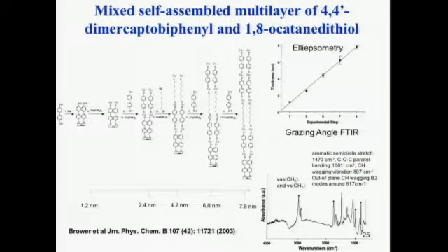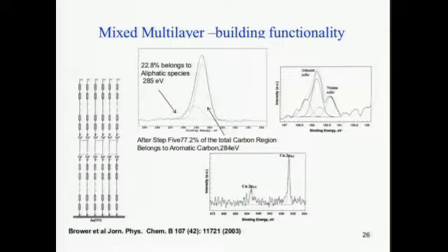In this case, you have the aliphatic system. This is a grazing angle FTIR sample of 3 layers. It's this one right here. You can see the aliphatic asymmetric and symmetric vibrational stretching of the carbon backbone, and you can also see peaks that represent the aromatic system, all in one spectrum. And then, of course, I always have the ellipsometry and so forth, and the thickness corresponds exactly to the number of molecules that I put in.